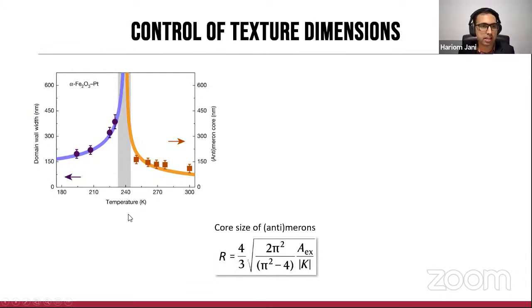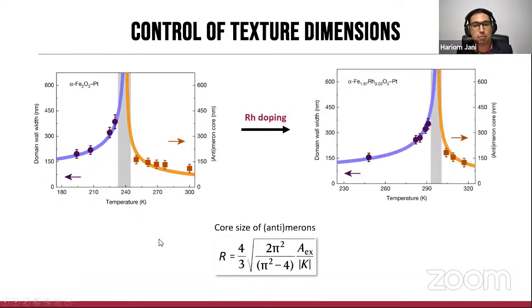We avoid fitting in the region very close to the transition because that's where the anisotropy goes close to zero, and therefore the size of all textures would diverge. As you saw in my previous images, this is indeed the case because we actually have a composition of in-plane and out-of-plane domains in this gray region, so we avoid that. But nonetheless, in the high temperature regime, we can actually clearly see that they are declining. Now, by doing rhodium doping, we can completely shift the position of the transition, and therefore we are able to completely redefine where in-plane and out-of-plane textures can be stabilized, and therefore there is unprecedented control over dimensions that can be obtained by doing careful doping.